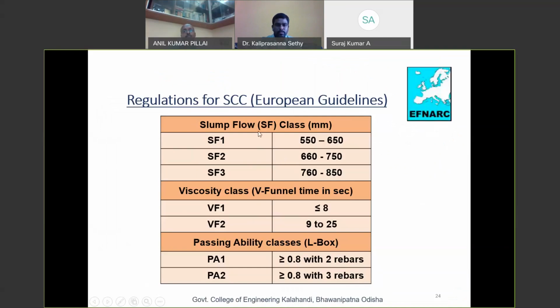Here are the limitations, meaning the guidelines given by the EFNARC European code. If the slump flow, that is the maximum flow, remains between 550 to 650, 660 to 750, or above, it will be categorized as SF1, SF2 or SF3. For the viscosity class, if the flow duration is less than 8 seconds, it will be categorized as VF1, and 9 to 25 seconds is VF2. For passing ability, if the ratio is greater than 0.8 with 2 rebars, it will be categorized as PA1, and PA2 for more than 0.8 with 3 rebars.